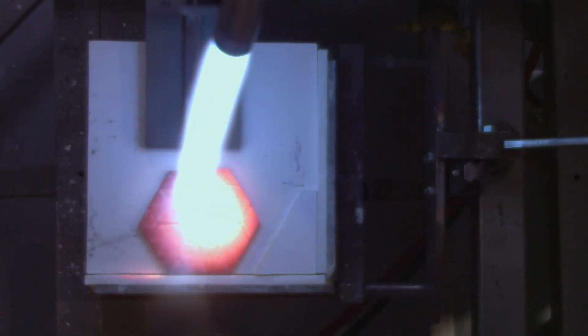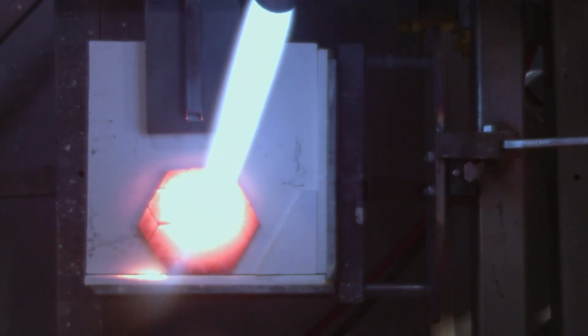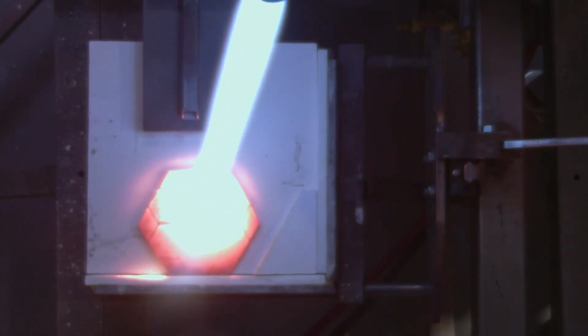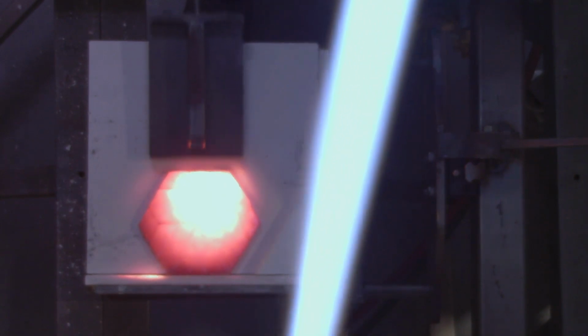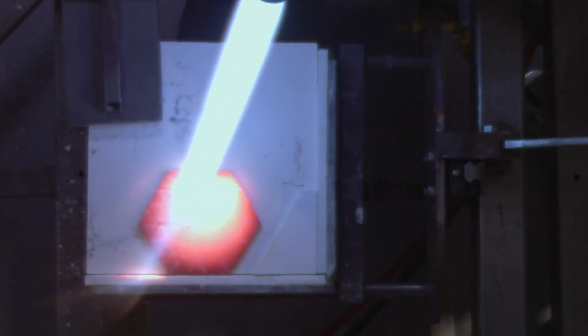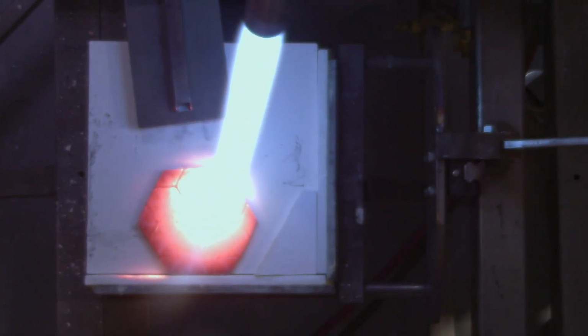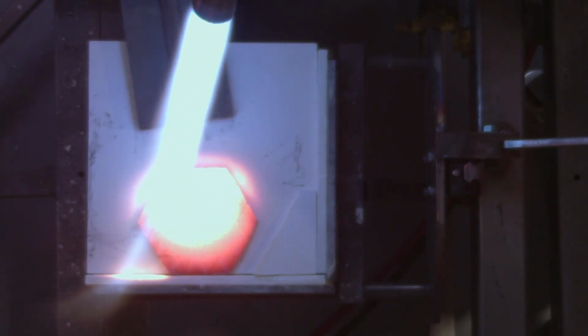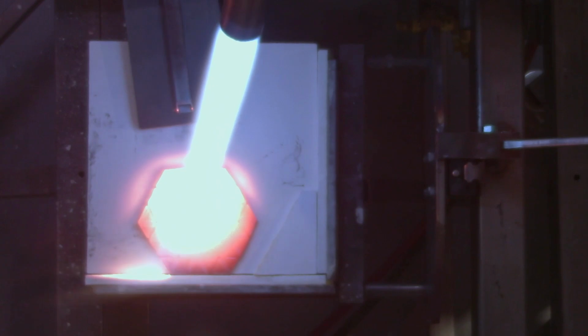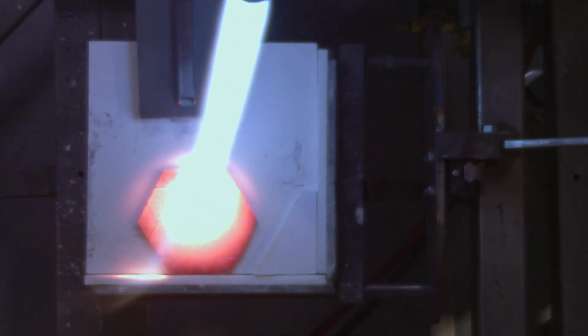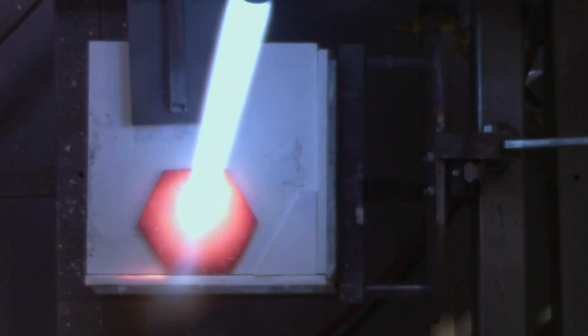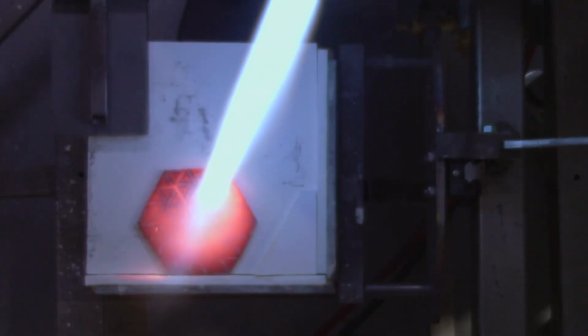So using the backstop on the fixture, it's sticking a tiny little bit, which tells me that I'm right at the edge where I want to be of getting it hot enough to be workable, but still when it sticks, it doesn't stick catastrophically. It just kind of barely sticks the littlest bit. And after a number of times practicing this method, I've realized that this is the perfect situation. When it just barely sticks the tiniest little bit, that's when I've got everything dialed in just about perfectly.